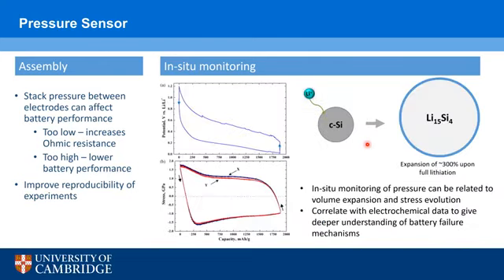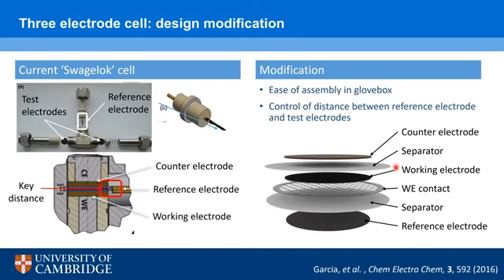And so what we propose to do with the pressure sensing is, by monitoring this in situ, so during the electrochemical cycling, we can then relate the measurement back to the volume expansion in the silicon, and get an idea of the stress evolution within the silicon electrode, and then correlate that back to electrochemical data to give a deeper understanding of battery failure mechanisms. Yeah, so I'll pass over to Liam now to continue the presentation.